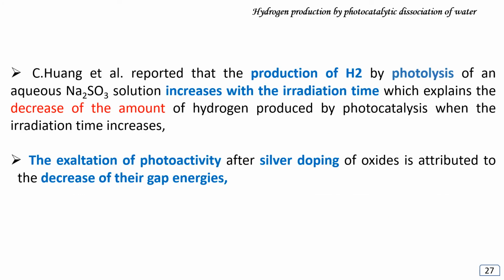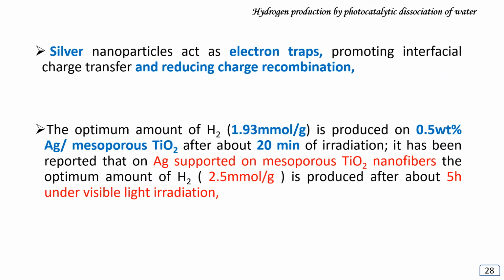C.Huang et al. reported that the production of hydrogen by photolysis of an aqueous Na2SO3 solution increases with the irradiation time, which explains the decrease of the amount of hydrogen produced by photocatalysis when the irradiation time increases. The exaltation of photoactivity after silver doping of oxides is attributed to the decrease of their gap. Silver nanoparticles act as electron traps, promoting interfacial charge transfer and reducing charge recombination.